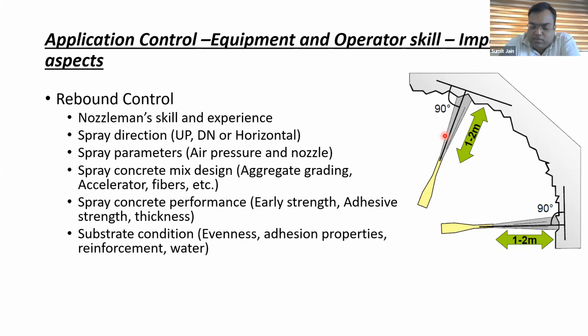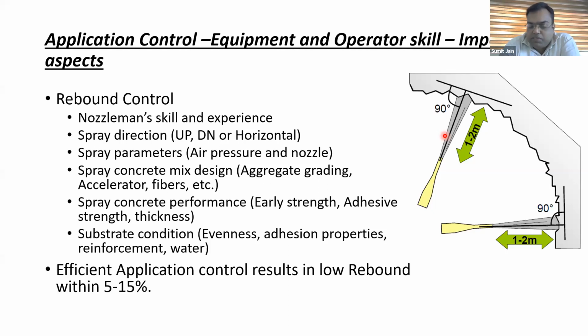If you have a poorly graded aggregate, then the rebound will be more. And then what accelerator you are using, how much is the dosage, all these things in the mix design affect the rebound. And then there is the concrete performance requirement, early strength and thickness of the application, and substrate conditions. If the substrate is uneven or there is a lot of water coming out from the substrate when you are spraying shotcrete, then that will result in more rebound. Now, efficient application usually can control the rebound within a range of 5 to 15%. So if your applications are within this range, then it's a good job done at the site.